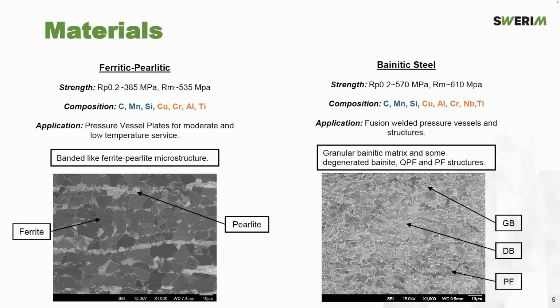Today I will present two different materials. The first has a pearlitic microstructure with a yield strength of 385 and UTS of 535. The main elements are manganese and silicon. It has some aluminum, titanium, chromium, and the main application is pressure vessels for moderate pressure and low temperatures. The second is a bainitic steel with higher yield strength and UTS, and mainly the same composition, more or less. It's used for fusion weld pressure vessels. And we have some granular bainitic matrix with some degenerated quasi-polygonal ferrite and polygonal ferrite structures.